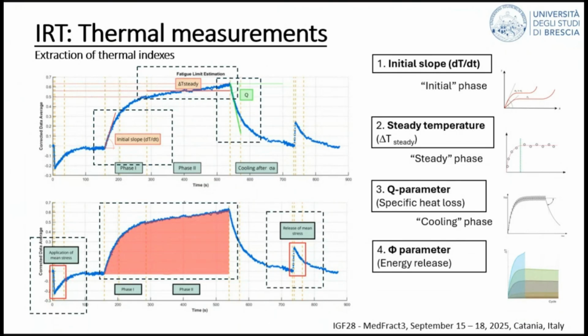And then you may have noticed that at the beginning and at the end of the test, we have these 2 spikes in the temperature. These are related to essentially the thermoelastic effect when we apply the mean stress and when we release it, separately from the cyclic loading at the end of the test.